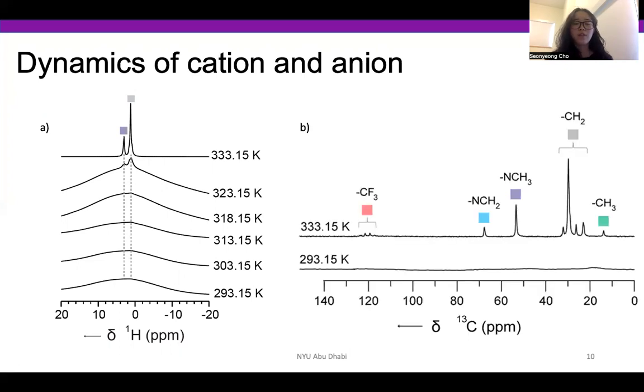And then looking at figure B, it is a carbon-13 solid state NMR without magic angle spinning. And again, at 293.15 Kelvin or 20 degrees Celsius, the spectrum is very broad and featureless, again, due to the anisotropic NMR interactions and lack of motional averaging. But with increasing temperature, you can see that the peaks are very well resolved. And from this, we can conclude that the cation and anions are dynamic, and they are averaging the anisotropic NMR